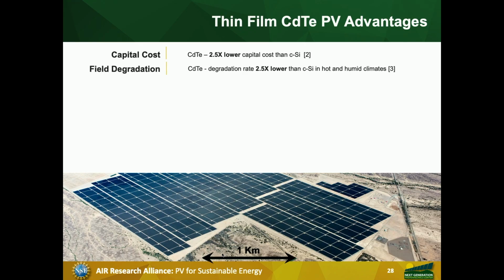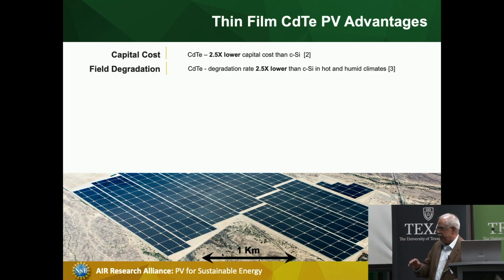Field degradation: cadmium telluride degrades 2.5 times less than crystalline silicon in hot humid climates. If you go to the Indian Institute of Technology, Bombay, they have how different modules are performing throughout India laid out on the map of India, and the one technology that meets the specification in terms of degradation is the telluride modules, that in cold climates, warm climates, in humid climates, it does very good.